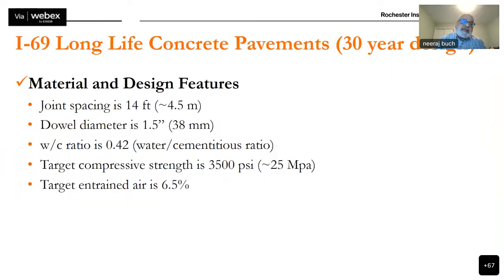So for the Interstate 69, the 30-year design, these are some of the basic structural and material facts. The joint spacing, these are all jointed plain concrete pavements. So there is no reinforcement in the body of the concrete. The only reinforcement that exists in this concrete pavement are at the joints, the transverse joints, as well as the longitudinal joints. So there are dowel bars in the transverse joints and tie bars in the longitudinal joints. The contraction joint spacing was about 4.5 meters, which is quite typical of jointed plain concrete pavements.